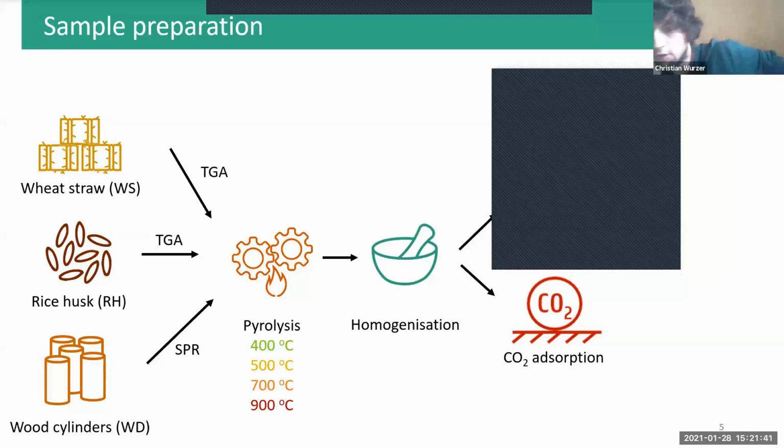We have another question from Juan. Are nitrogen adsorption BET methods reliable to measure biochar surface area in the order of 10 to the -1 square meter? No, not at all. In general, it's assumed that for specific surface areas around 10, 20, in that range, the sample mass has to be around 1 gram or even more. Yes, like 2 grams, because